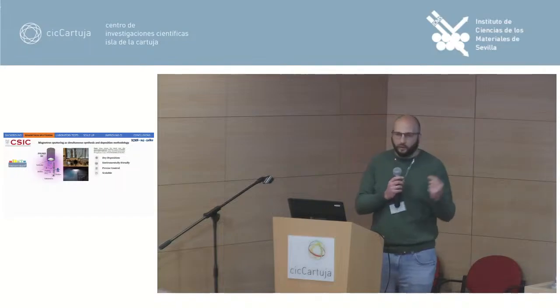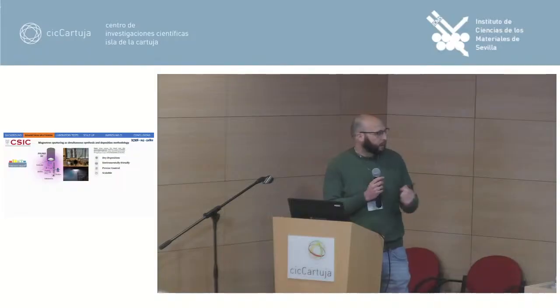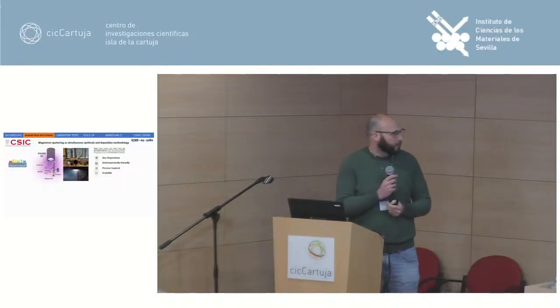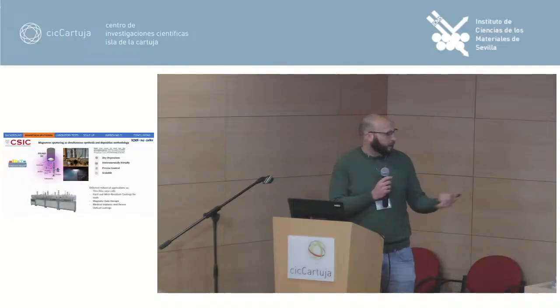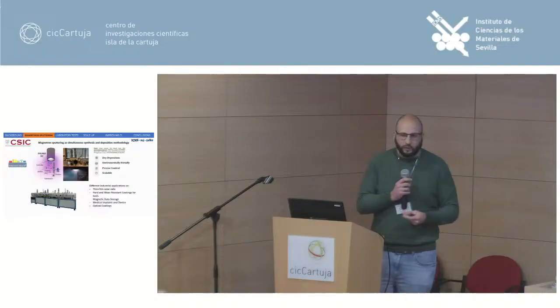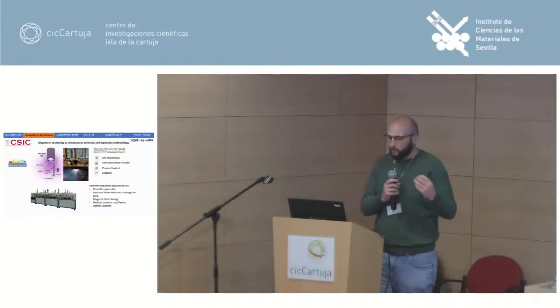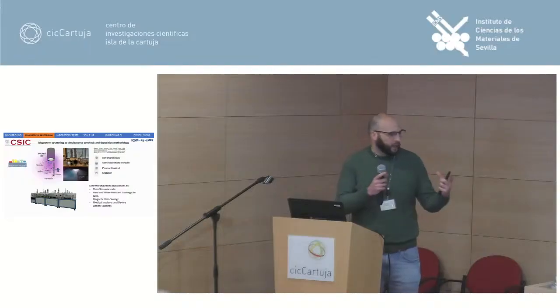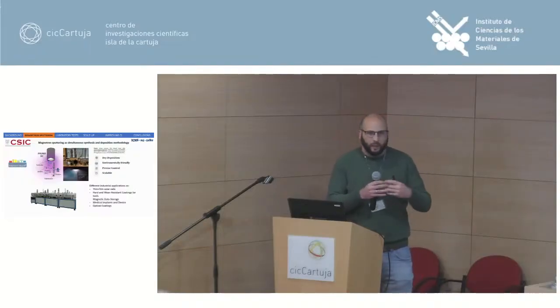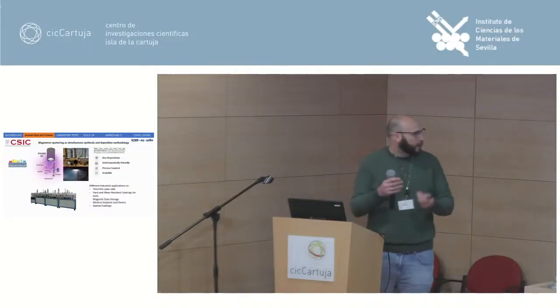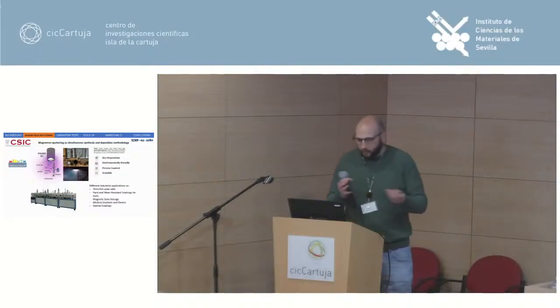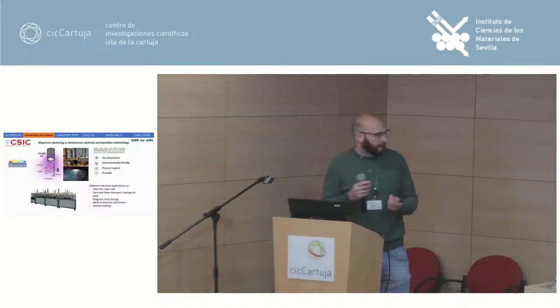This is relevant because this helps to control the composition of the layer, its thickness, and also we can modulate its properties to make it more active for our application. And additionally, this is a technique that is widely implemented in the industry. So it's a technique that is very proper if we want to obtain electrodes at large scales, or if we want to deposit a large amount of surface, and then obtain a big amount of electrodes that will be used in the industry. To summarize, it's a technique that is highly scalable.